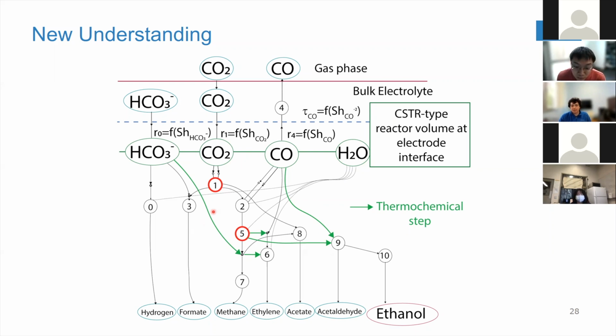And what we identified is that it's very likely that you take CO2, you make CO. That CO is reduced to some sort of carbon species at the surface of the electrode. Depending on the residence time of that CO and the probability that it is lingering around at the surface of the electrode, you increase CC coupling. If you don't have a lot of CO, then that carbon will be further reduced to make methane. And then the same carbon reaction intermediate will be an intermediate for acetaldehyde production and ethanol.